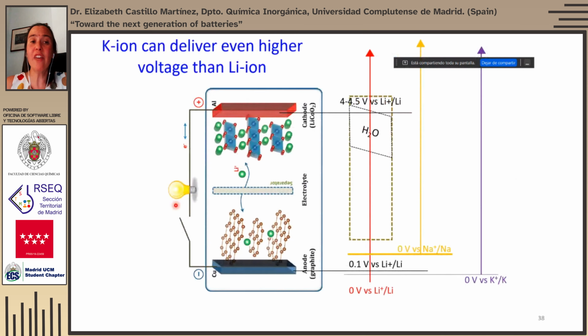If we move from sodium to potassium, we can see that potassium ion does plate at voltages which are even below lithium plating, and therefore, in principle, one could even achieve voltages higher than those of lithium batteries. However, of course, there is a penalty on the weight of the potassium ion for the gravimetric energy density, and most of all, the main concern is that actually potassium metal is quite reactive, and we want to avoid potassium plating. And therefore, even though the voltage is lower, we will look for anode materials which are not very low in voltage or very close to potassium. Nonetheless, many people are looking into safely plating potassium, as this appears as a possible high energy density battery.